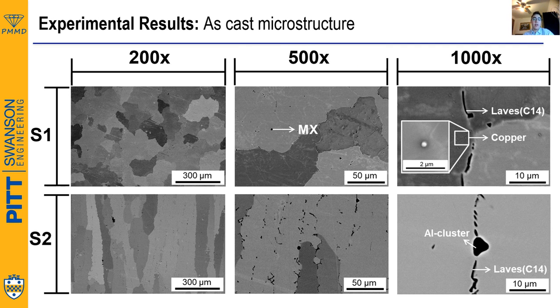Here in this next slide, you can see backscatter images of the as-cast microstructure of both samples S1 and S2 at 3 different magnifications. And we indeed see that the CALPHAD predictions for the non-equilibrium solidification behavior are confirmed. EDS results not shown here confirm that the black discrete squiggly features that you can see are predominantly the Fe2Ti C14 Laves phase, while the black squarish features correspond to the MX or the titanium carbide phase.